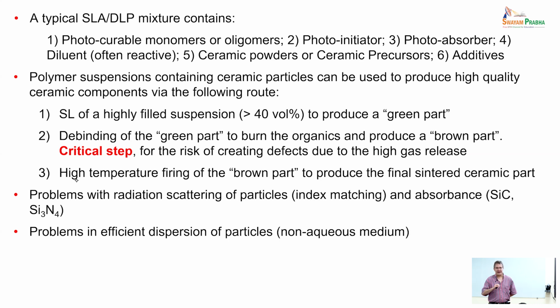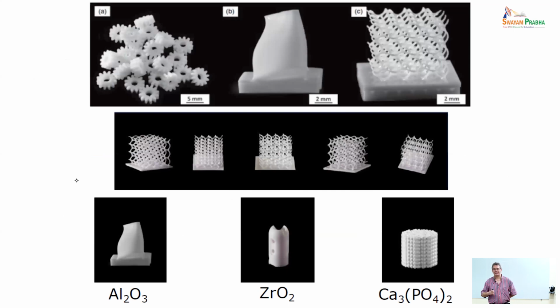For non-aqueous systems, so if you have to disperse ceramic particles in a polymer, the chemical ways of doing that efficiently are much more limited. So having a homogeneous and stable slurry matters, because with conventional DLP, SLA, it takes hours to print a part. So you need to have a slurry that is stable for a long time. So this is certainly a problem for using these types of technologies with ceramics. But you can see here that people are actually able to use these technologies quite well. Here are different parts. They don't necessarily have any applications, the ones in the middle, but they show the capability of the technology. And these are parts made of alumina, zirconia and calcium phosphate, which is a bioceramic.